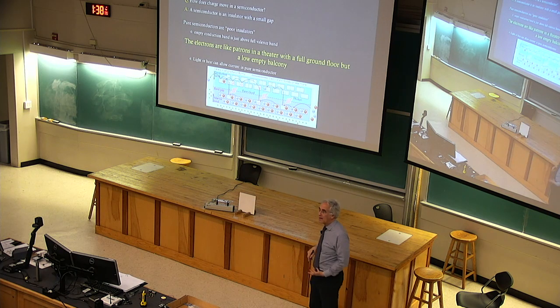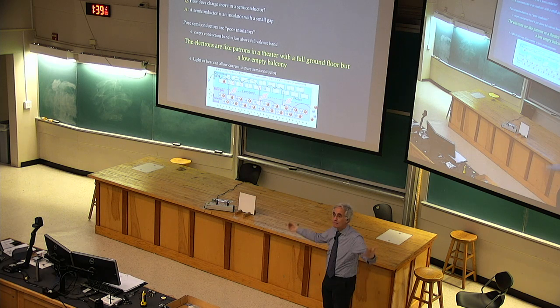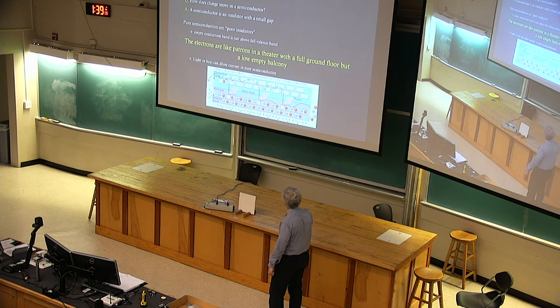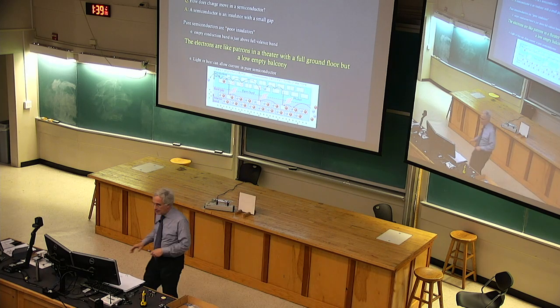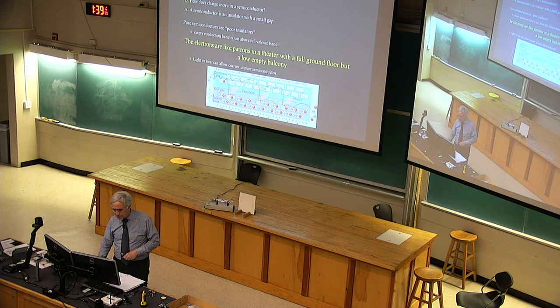They apply a coating on that drum that is an insulator in the dark and in the cold, because all the electrons have piled into the valence band and below and filled it, and the conduction band's empty. But you expose it to light, now the electrons can move from valence levels to conduction levels, and now they can move. Questions? This is back to the xerographic copier. So light can turn these guys into conductors. All right.